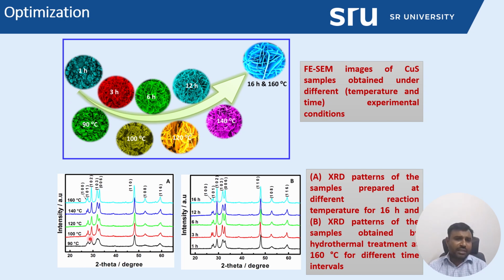Further increasing the temperature from 120, slowly the peaks are getting very strong, and we get a highly intense peak at temperatures of more than 140 degrees. So from this XRD we can clearly confirm the time and temperature play an important role in achieving a highly uniform copper sulfide flower-like morphology.